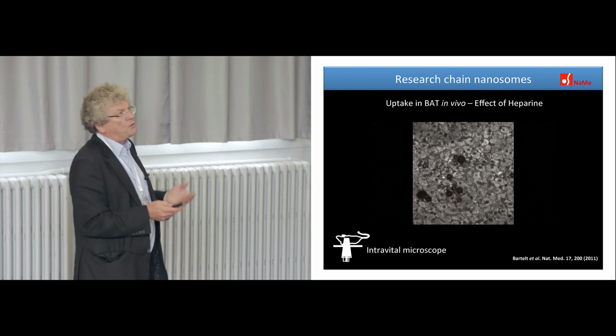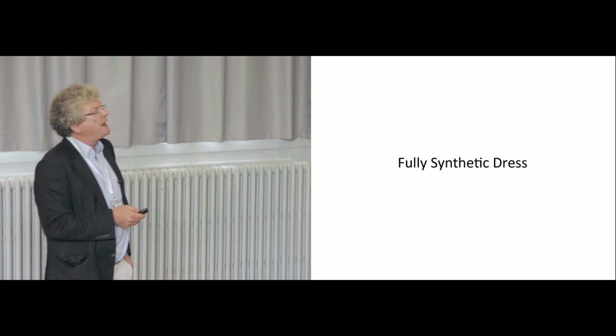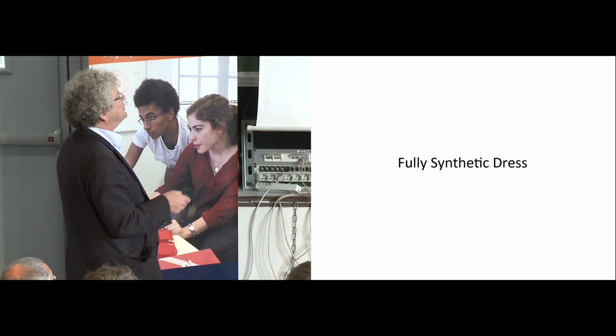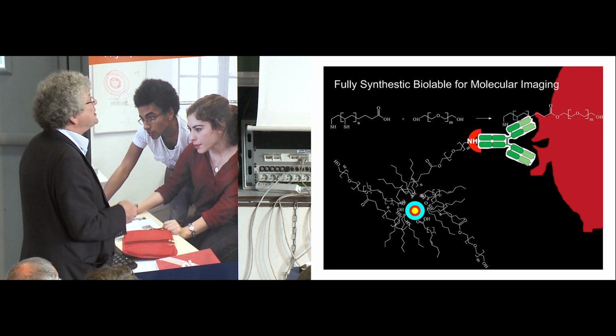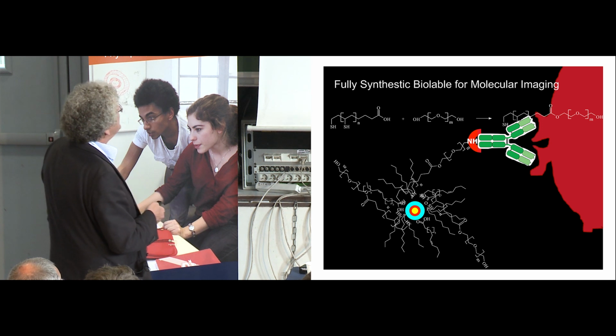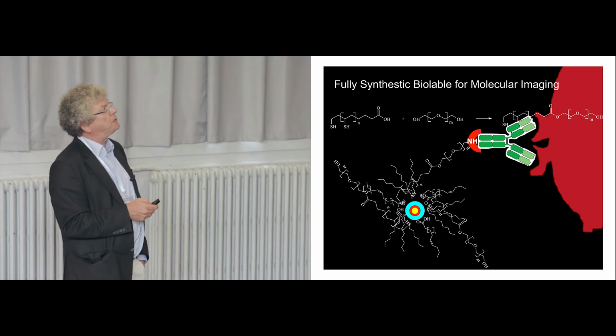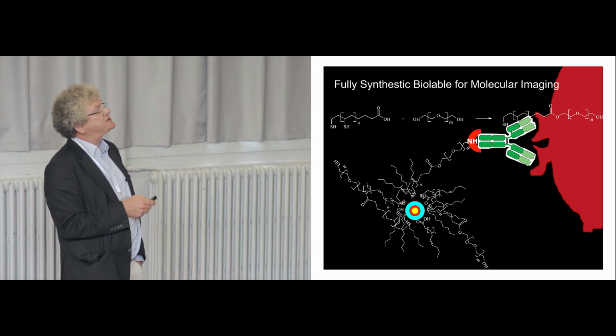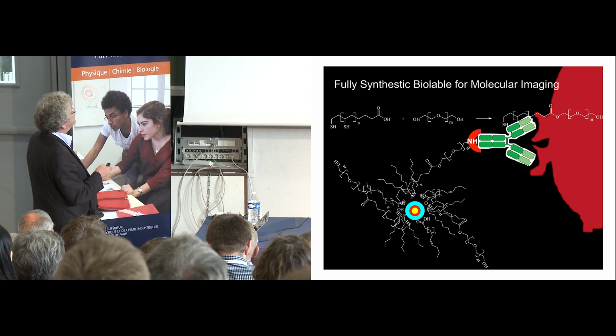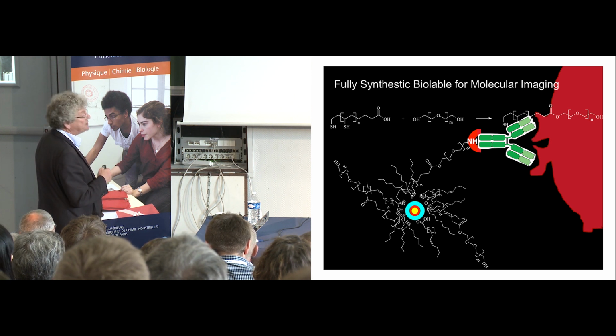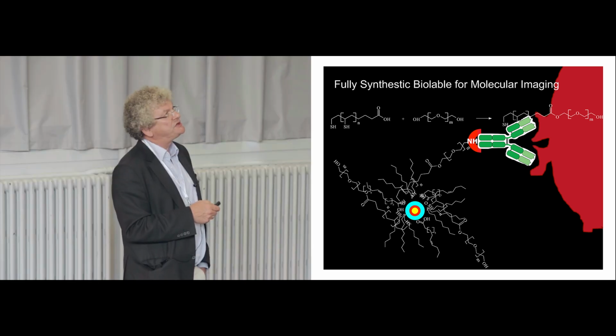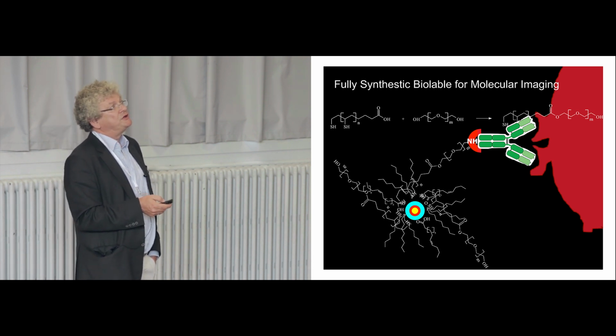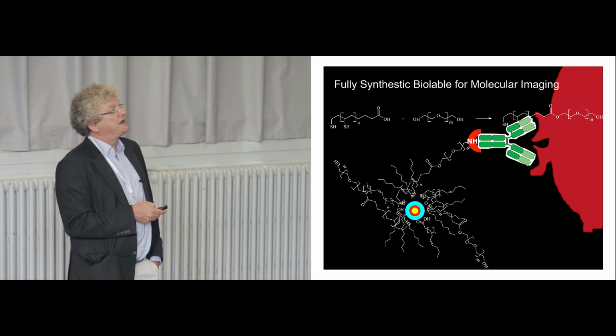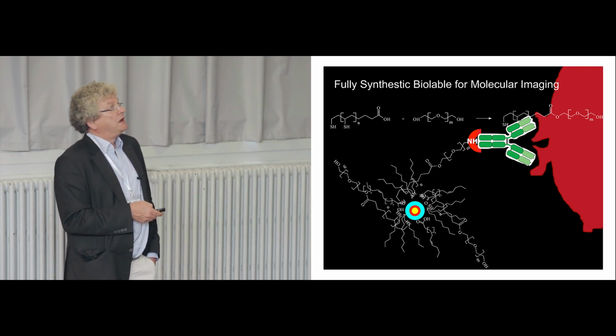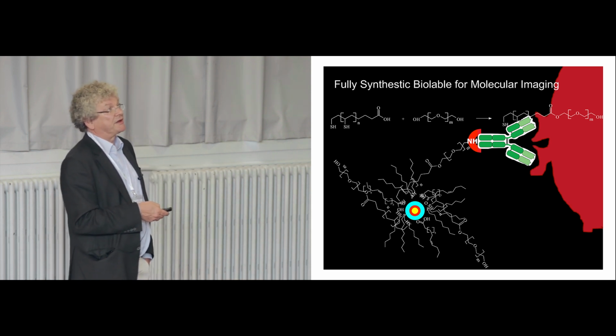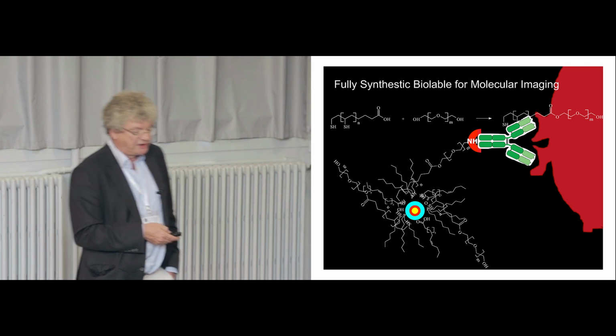And that was something where different strategies are meanwhile reported, of course, and you have to get rid of the original surfactants, like TOPO, oleic acid or others, and you have to exchange them against others. And many concepts, or one which we also follow, is making some ligands consisting of an anchor group, best with various multiple adsorbing functional groups, so multivalent attachment, and then some stealth function like PEG, polyethylene glycol, making new molecules, exchange them at the surface, and functionalize them, somehow conjugate them to antibodies or something like this, and hope you are able to make some delivery.